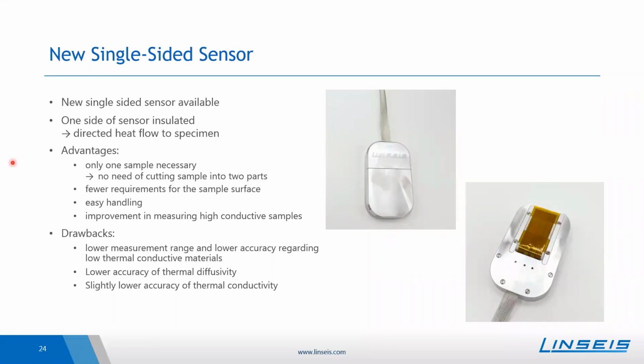As typical, if there are some advantages, there are also some disadvantages or drawbacks. Here, the problem with the single-sided sensor is that lower conductive materials are not easy to measure. One has a lower measurement range and a lower accuracy, because the difference between the insulation material and the sample is not that strong, and by that the accuracy is lowered. Additionally, the determination of the thermal diffusivity does not work as well as with the two-sample setup, because one has just the insulation material on the one side. Also, the thermal conductivity determination has a slightly lower accuracy compared to the two-sample setup.